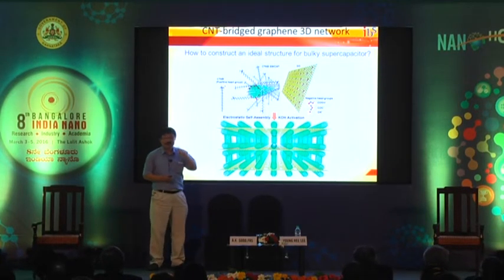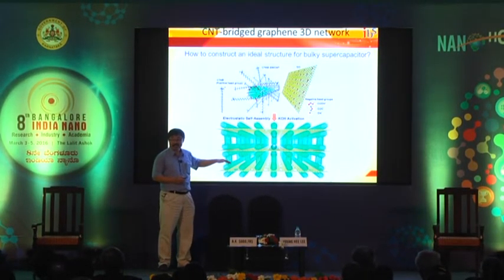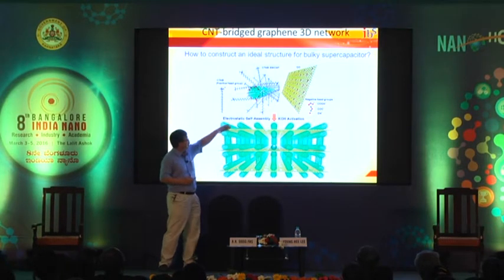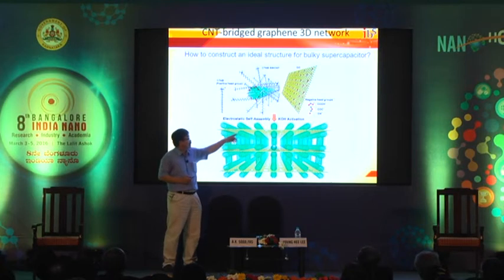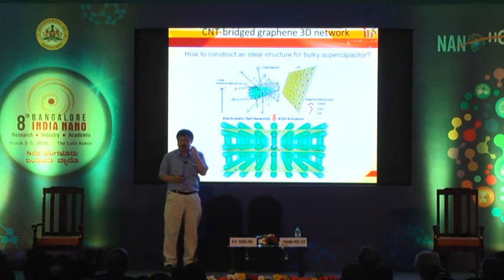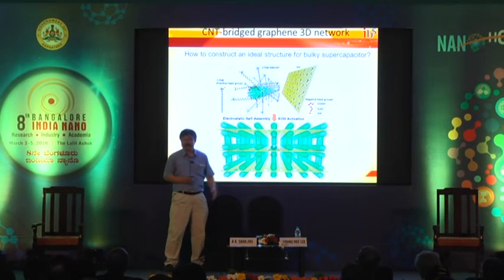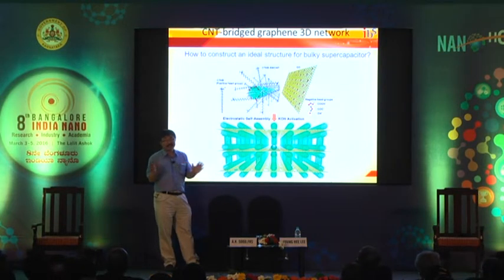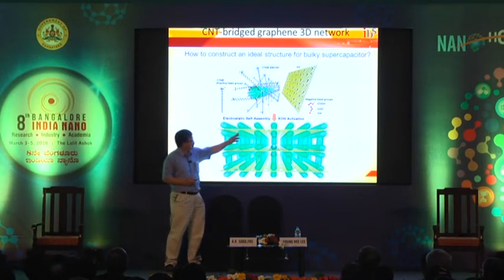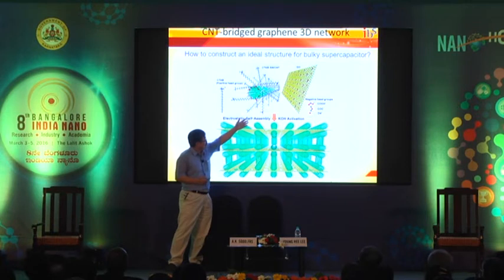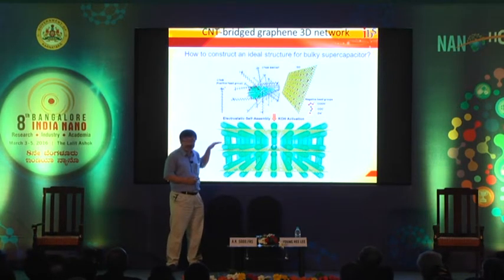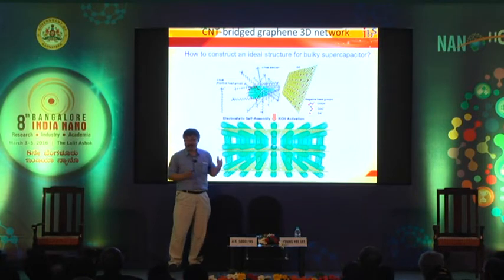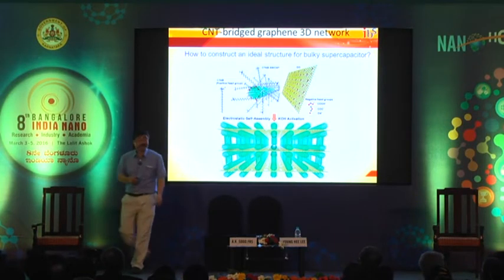Okay, we had one more treatment. Even though you have these three-dimensional building blocks, because graphene blocks ion diffusion, we have to create some kind of small pores by using KOH activation. The process is very simple, so we can optimize this. So ions can of course go through this channel very easily, but also through this graphene layer as well. So this is the key.